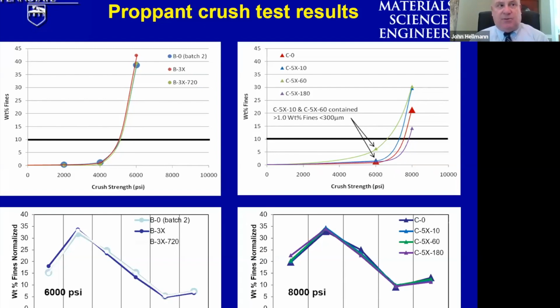Now, a crush test from the American Petroleum Institute entails taking an assemblage of beads in a die, applying a uniaxial load to different levels, sieving the materials in between loads, and when 10% of the materials is produced as fines, that's considered the crush strength. Pretty empirical, but it's used widely by the industry.